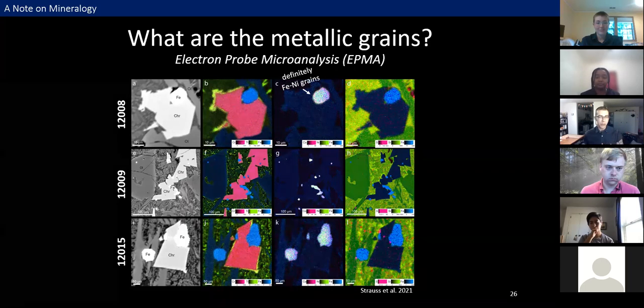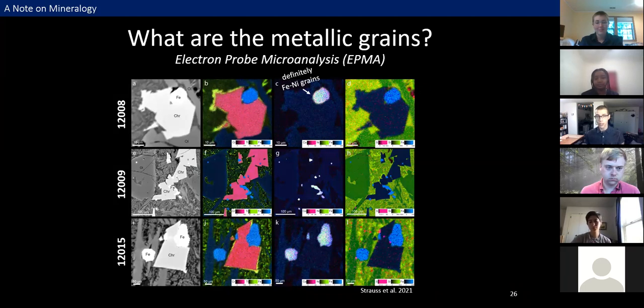But I want to point out a few other major things that we noticed as we were searching for them. First, we found grains with different iron nickel ratios in each sample, and we were able to identify both kamacite and martensite. In fact, we mostly found martensite, while other studies of different basalts have found mostly kamacite, which is kind of interesting. We also found that many of these iron nickel grains are not homogeneous, so you can see some compositional gradients in the grains that I'm showing here. We also observed some bright submicron sized grains that were unfortunately too small to acquire quantitative points from, but from all of that, we can say that we observed multiple sizes of both kamacite and martensite, which is pretty exciting.